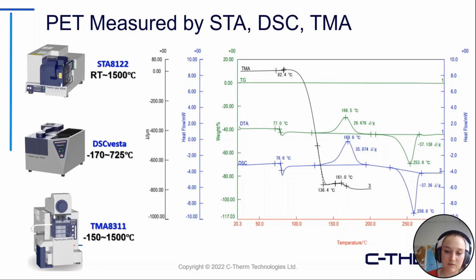For the DSC, we can also see the glass transition, and we can see the exotherm there as crystallization, where the sample slightly expands at crystallization, as you can see on the TMA curve. So testing with DSC, STA, and TMA is important for a polymer such as PET, so you can fully understand the material properties for processing and also for use in products, in addition to the manufacturer's data sheet, of course.